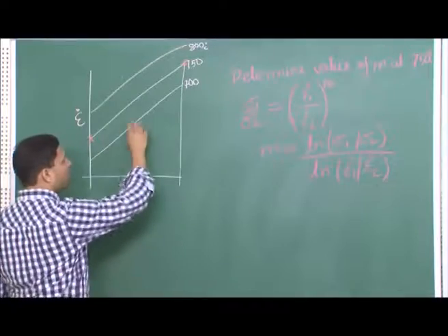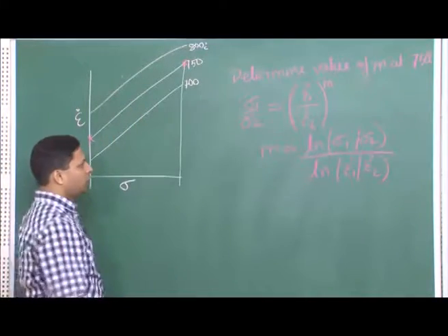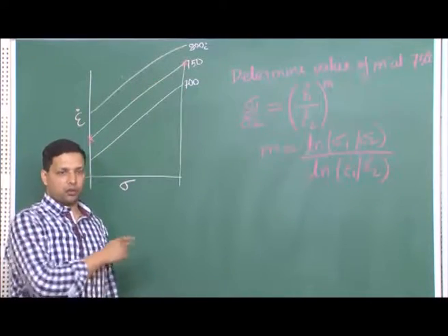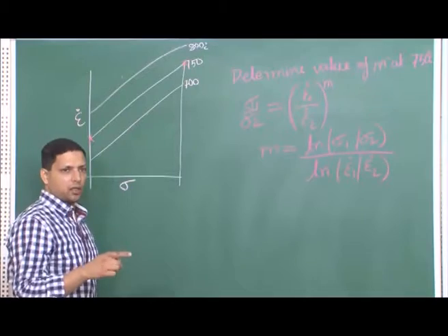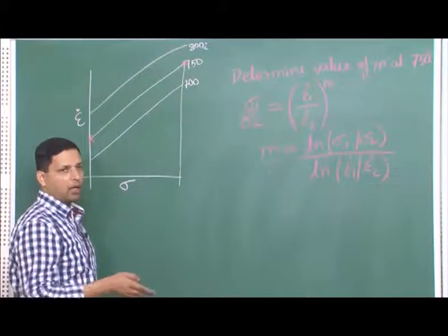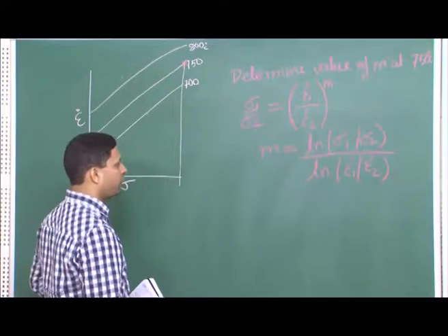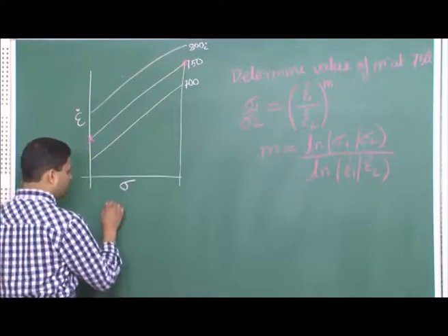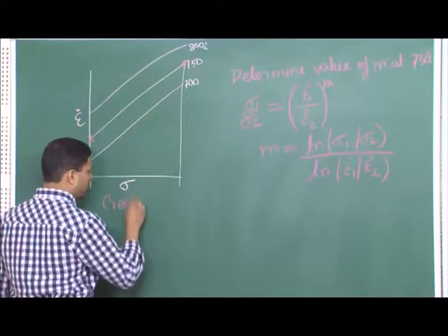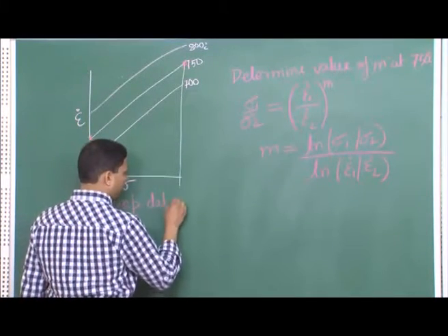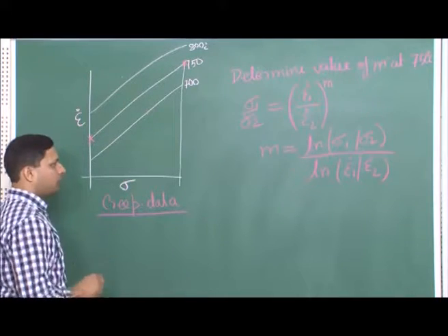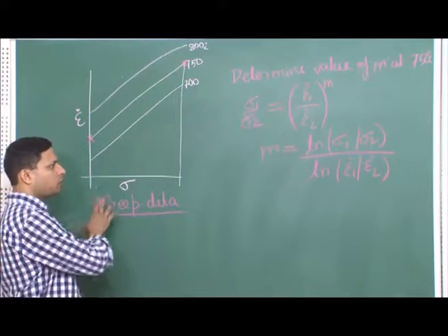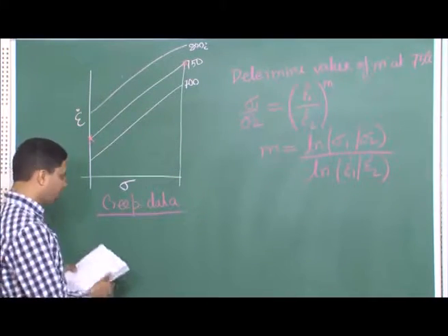Whatever temperatures you have recorded the data for, you will have m values, and then you can even plot m as a function of temperature, and then you can see that it actually increases slightly up to 0.5 Tm and then suddenly takes off after 0.5 Tm. So, that is one piece of information that you can extract from this. Let me write it again, this is creep data. From an experiment like creep, you can obtain values like this and make a plot like this, and from those plots you will be able to extract information. So, this is one thing.